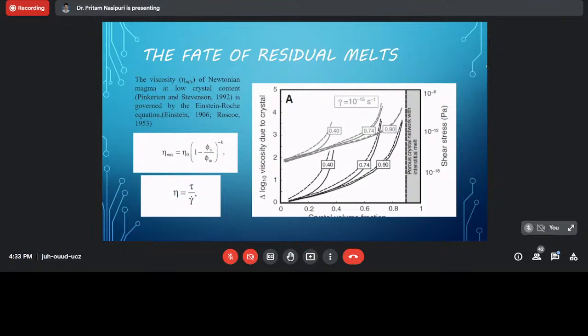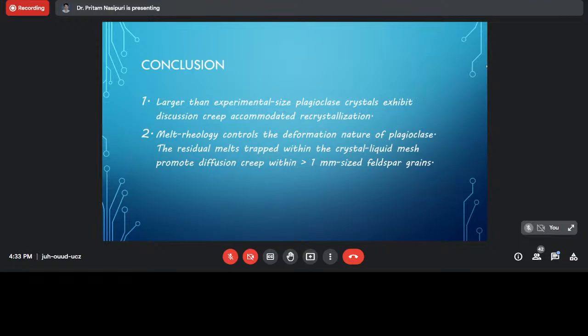natural system. So to conclude, I can say that first, this is the example where larger than experimental size plagioclase crystals can exhibit diffusion creep accommodated recrystallization, and it is finally the melt rheology, where it comes to the geochemistry, that controls the deformation nature of the plagioclase. And the geochemistry of the melts, which is the viscosity of the residual melt that is trapped within the crystal liquid melt, promotes the diffusion creep within the feldspars, which are greater than 1 millimeter size feldspar grains, at least in the case of Bolangir Pluton. So this was my talk.